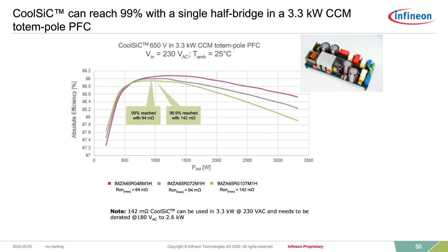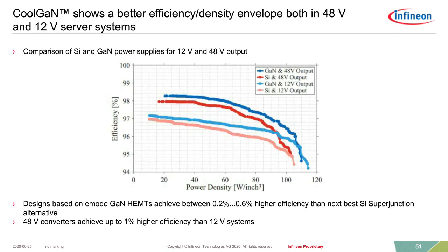Comparing now all technologies to each other, so silicon versus gallium nitride, in both 12-volt and 48-volt. What you see here on this chart is the so-called Pareto front, where you see on the x-axis the power density and the efficiency on the vertical axis. The 12-volt is the two lower lines, the 48-volt are the two higher lines. And you see that gallium nitride is always ahead of silicon. The distance is relatively small.